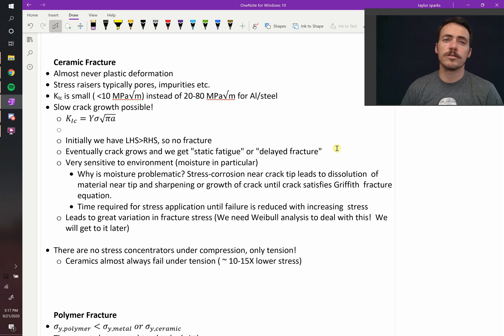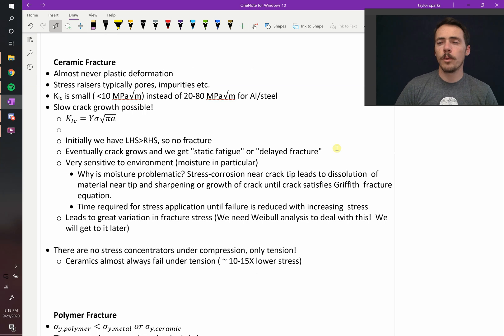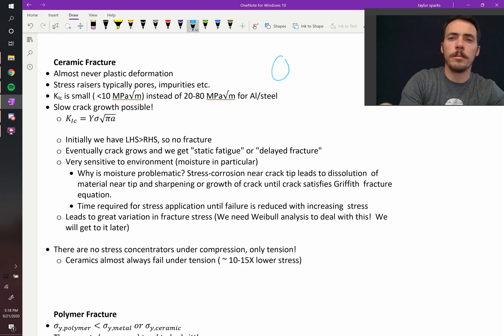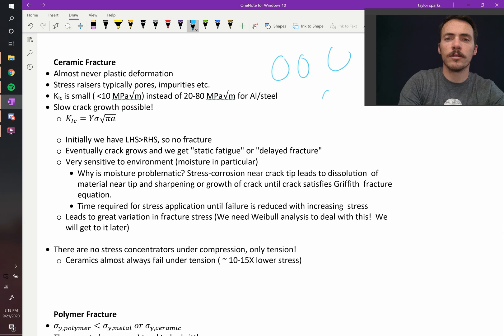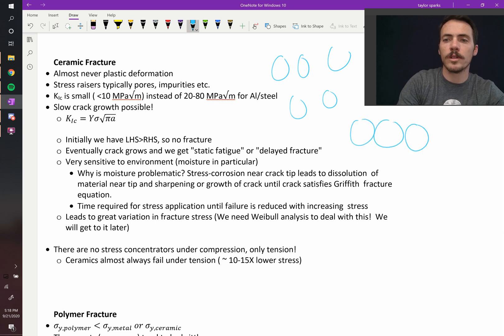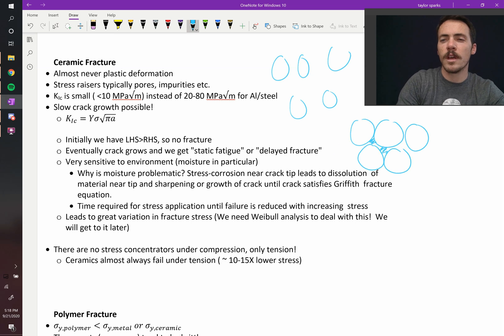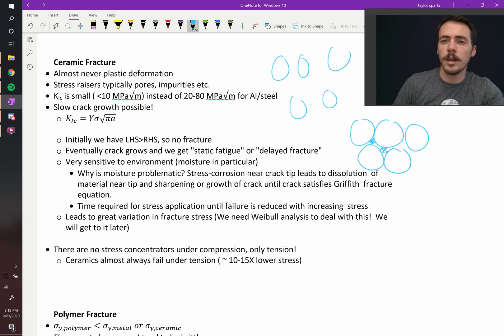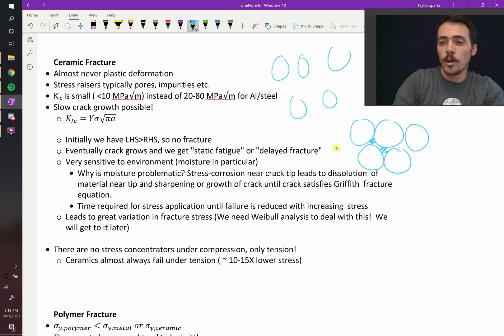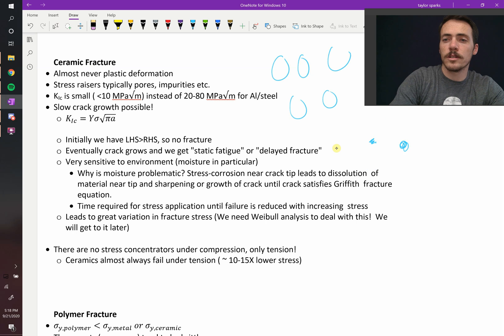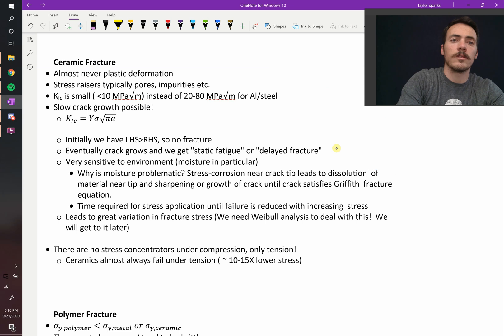The stress raisers or concentrators are typically things like pores and impurities. Pores because when you make ceramics, you start out with a bunch of independent particles and then you merge them together. And so as they come together, you end up with these interparticle regions, and you have to completely get rid of those regions. And that can be challenging to do. We'll talk more about that a little bit later when we talk about diffusion. But if you don't get rid of them, then you're left over with a pore inside of your material at those junctions. And those can be stress concentrators.